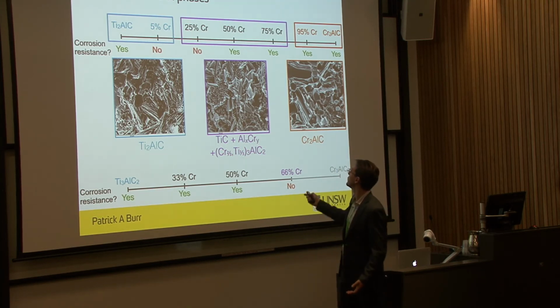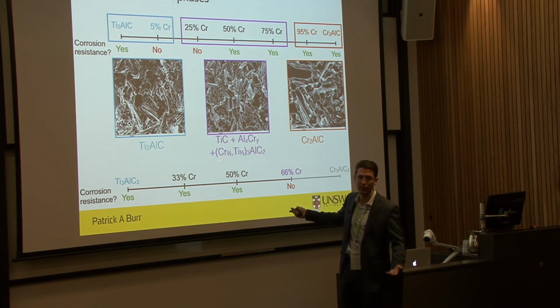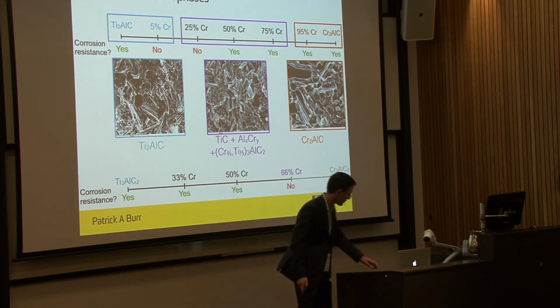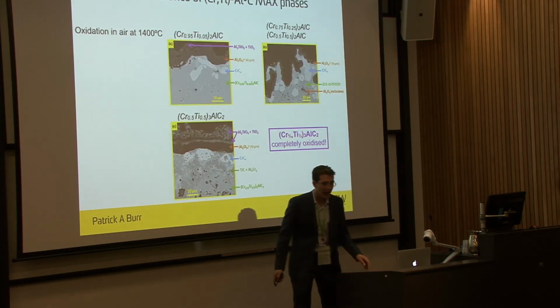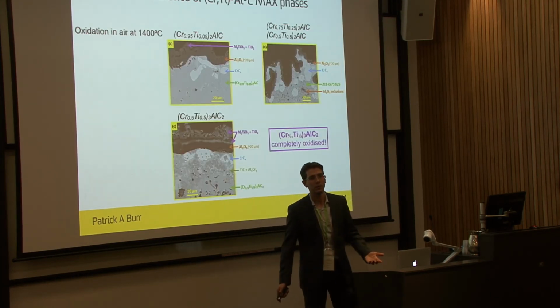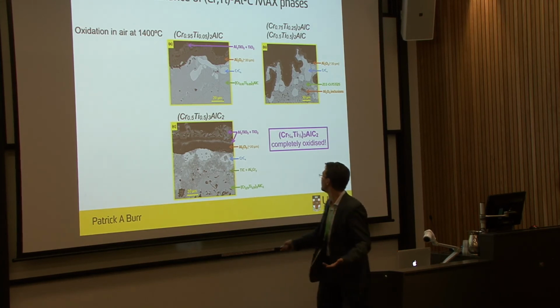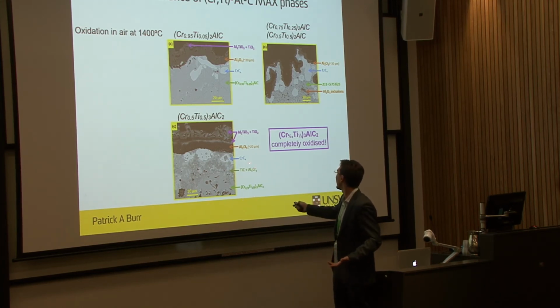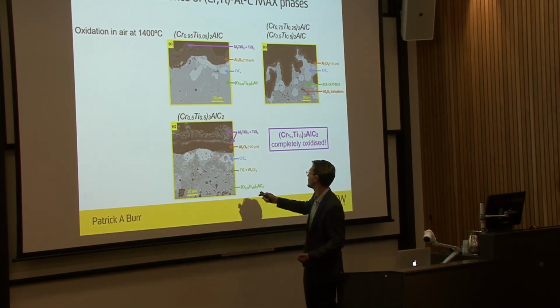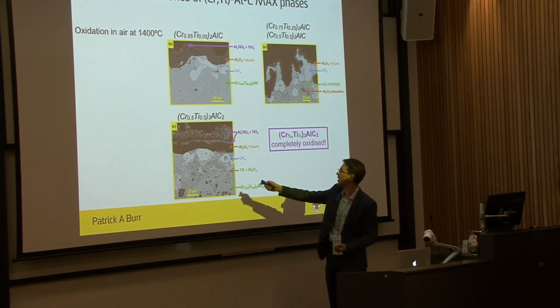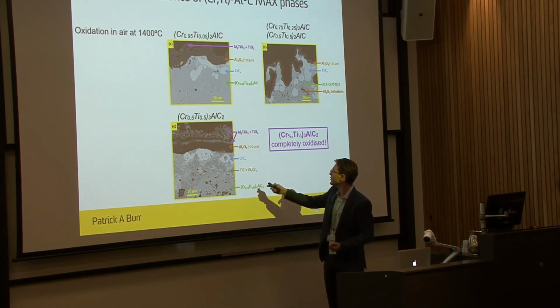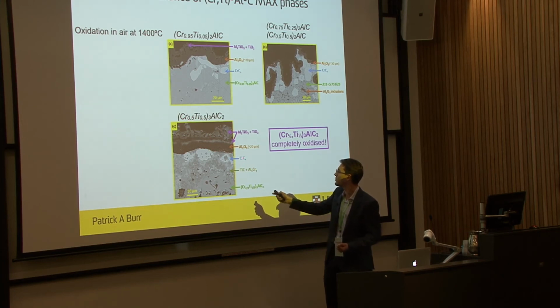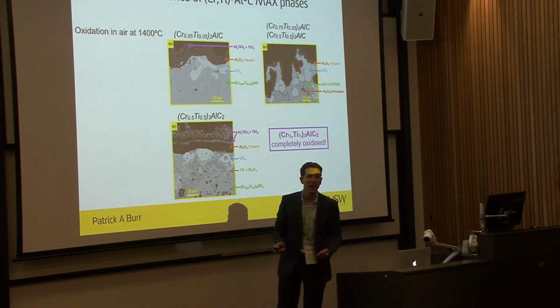From a practical point of view, the most oxidation tolerant were actually these ones. And it wasn't because of the MAX phase, because we know that MAX phase is not very oxidation resistant. It's actually because of all the other stuff that we were trying to avoid. So you get things like, this is the example. This is the most oxidation resistant sample we have, which has got a nice alumina layer. And it's because of this aluminum chromate and the chromium carbide that you form there.